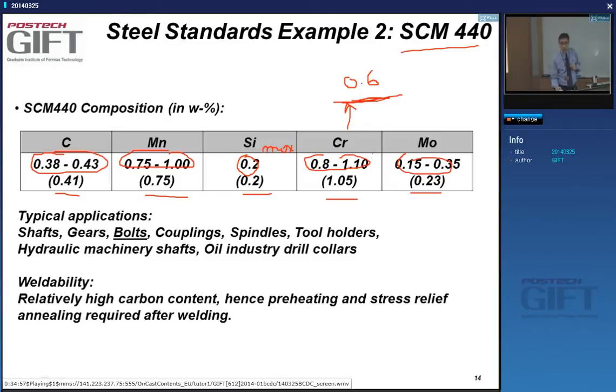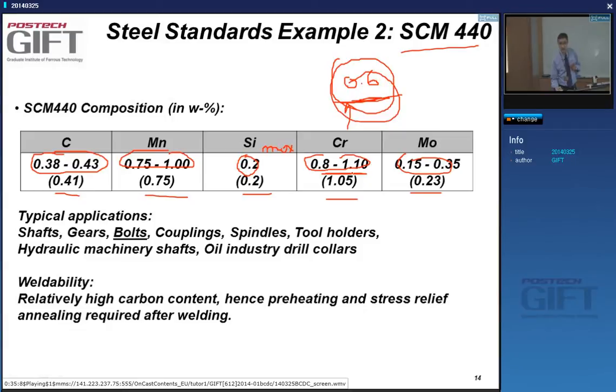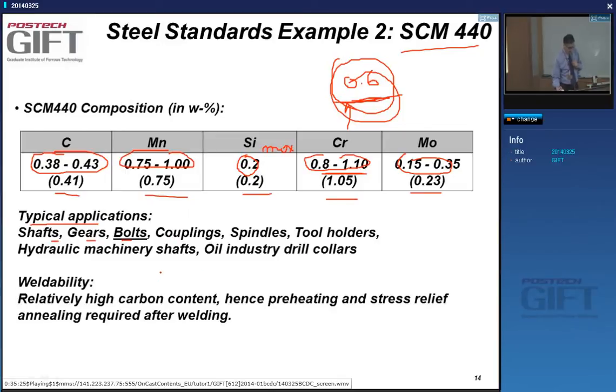But if a steel maker sells a steel under this name with a chrome content outside the specification range and there's a problem with the product, this will be a major issue — the grade specification for composition is very strict. Typical applications include bolts, gears, shafts, couplings, spindles, in general machinery applications. The carbon content is relatively high, meaning welding may be difficult — you'll need to preheat and stress relieve after welding.